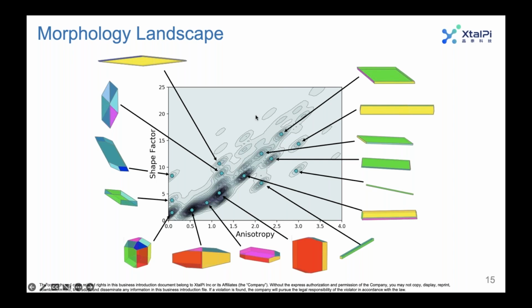This is a concept we developed at XtalPi. This is a way of thinking about all of the ways that a crystal could potentially grow, so all of the morphologies that you could potentially obtain for a crystal. The way we do this is we take the crystal structure and we calculate the morphologically important faces using the BFDH method. And then we use some descriptors, specifically the shape factor and the anisotropy, which are essentially two different ways of measuring the deviation from a sphere.